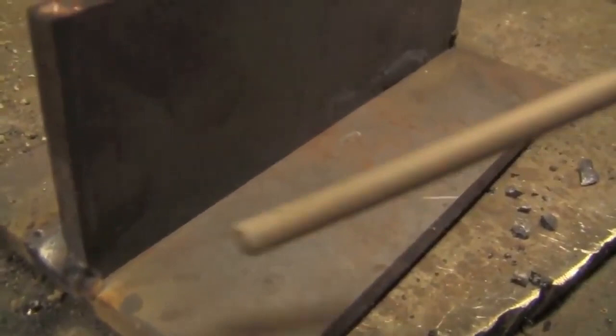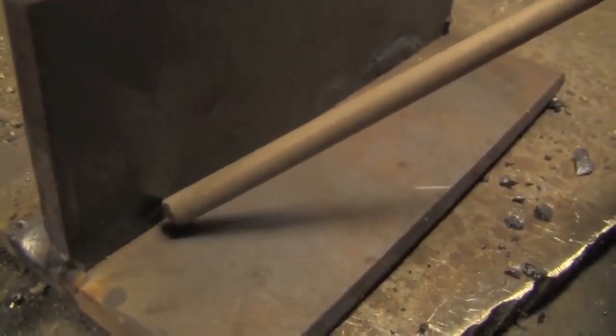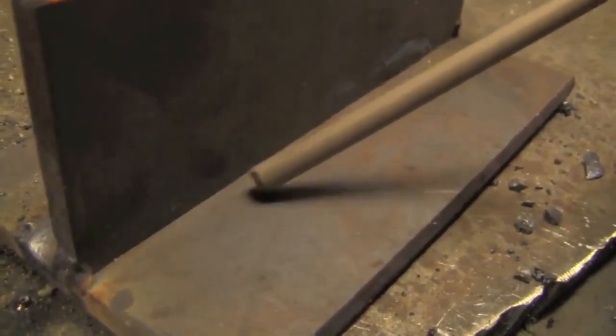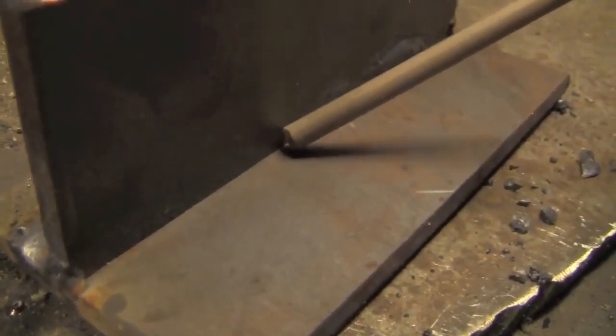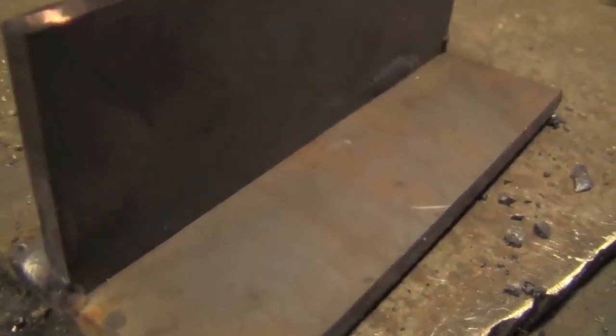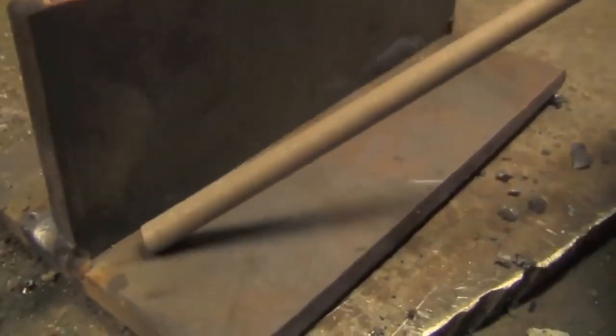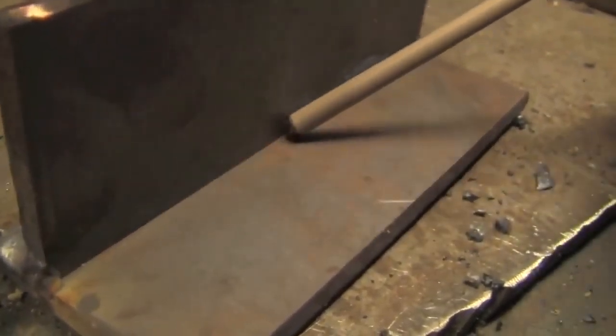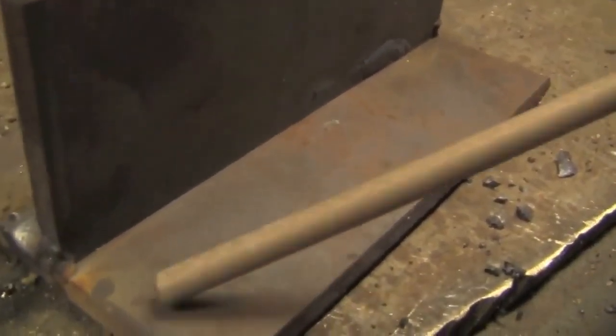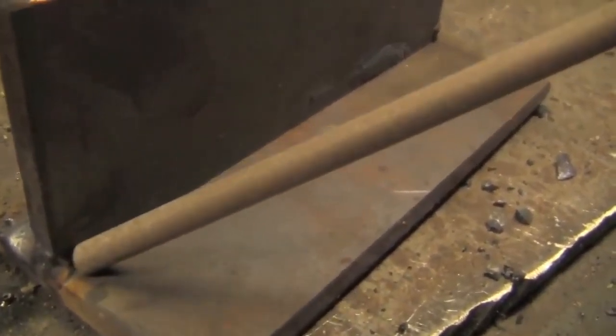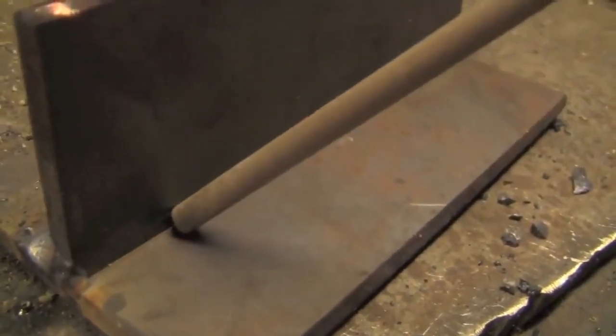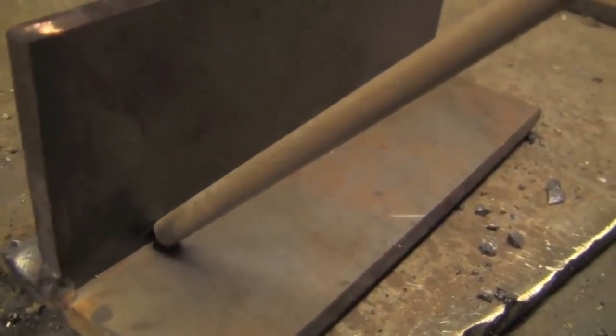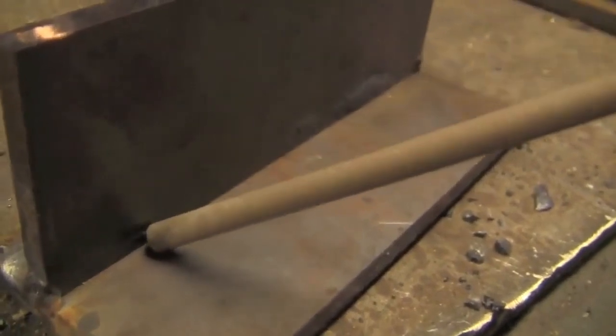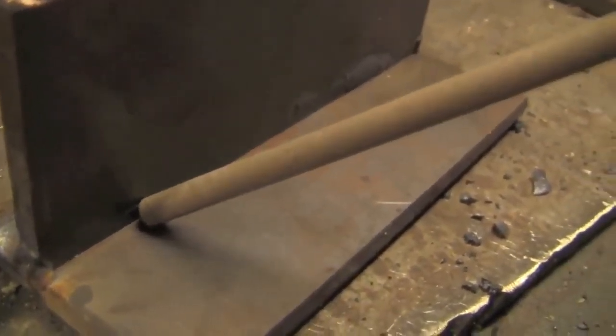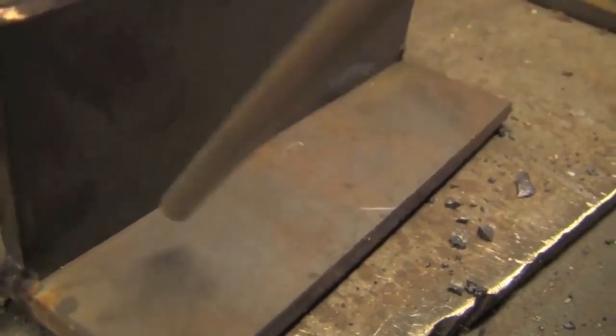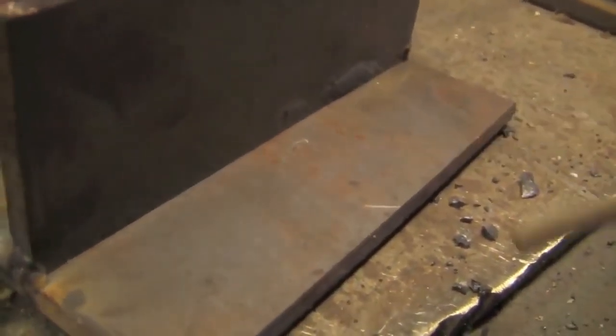But basically what that means is you have to drag this along and let the force of the electric arc push that slag back, and when it gets pushed back it stays out of the puddle, and then you don't have the huge wormholes that I'm hoping to generate here. It's important to use a pretty substantial drag angle with 7014 because it has a very heavy layer of slag. Other electrodes like 6010, 6011, 7018 are a bit more forgiving, so you can come up a little bit. A number of people that have experience with MIG welding don't really understand that concept because obviously there's no slag with MIG, so they'll try to push a stick electrode and get lots of nice big holes in it.